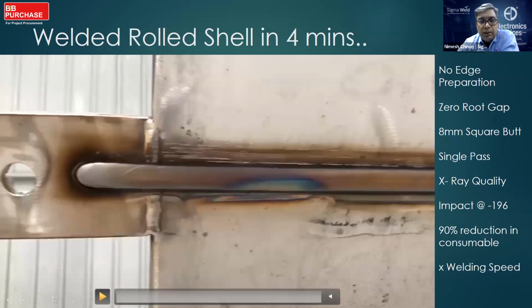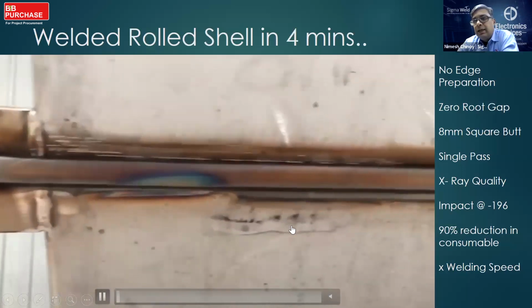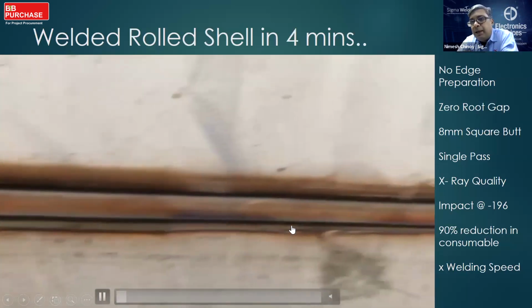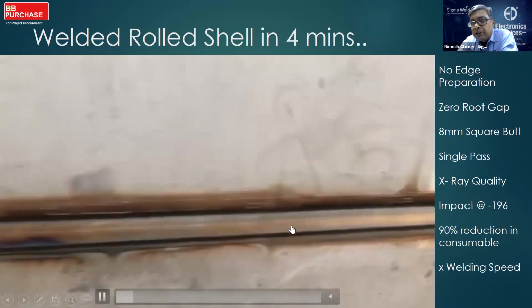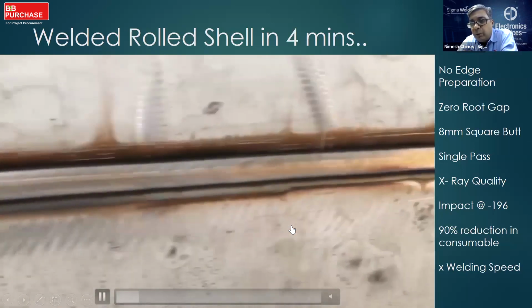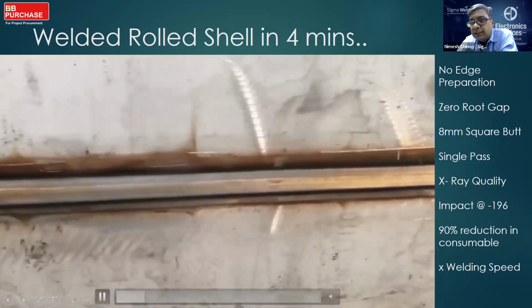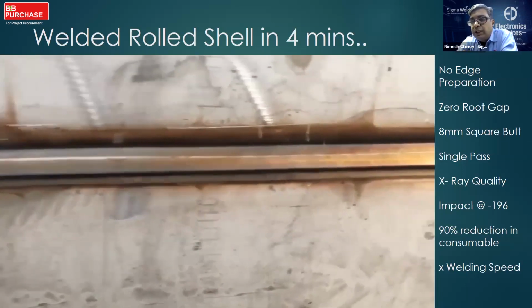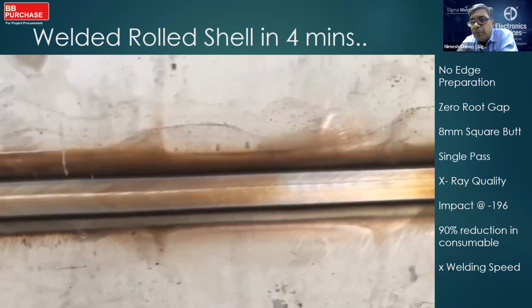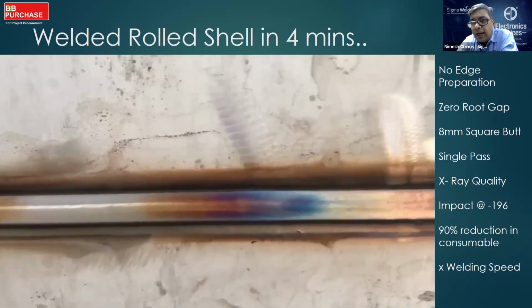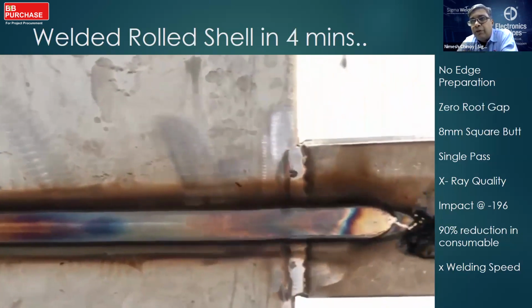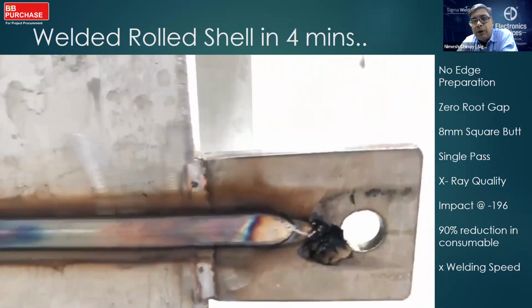This is for a customer doing cryogenic vessels. They had a 6 and an 8 millimeter thick shell, single pass, no edge preparation, X-ray quality weld, including impact at -196. They were able to reduce their consumable wire consumption by 90%. And this entire shell was welded in under 4 minutes. That's a 1.6 meter long shell welded in under 4 minutes.